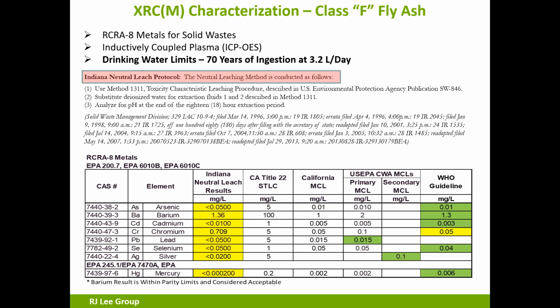So we've developed a couple of testing methods to determine whether or not this stuff is indeed going to cause harm. Back when the Class F was done, we were using the RCRA 8 metals to determine whether or not it was harmful, ICP for analysis, and drinking water limits. So we set up a leach using Indiana Neutral, which was designed specifically for fly ashes going back into the mining community. It is a neutral leach method using deionized water, which is to reflect rainwater.